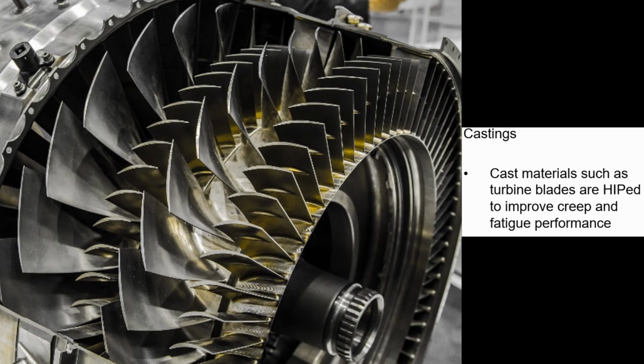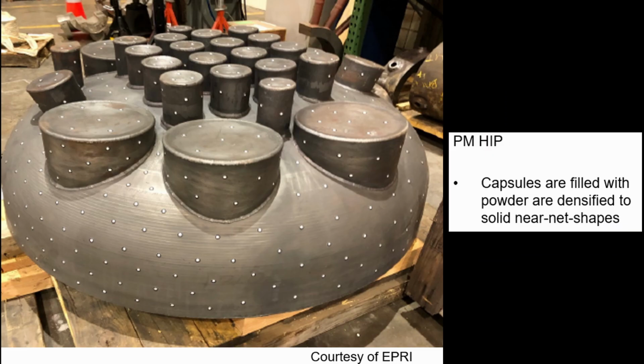One is densification, because castings have been densified since the 60s to improve fatigue life, etc. We have powder capsules, densification of powders, which is, like I say, since the 70s, really, which is really growing right now. It's a very interesting area. And then you have diffusion bonding of materials together, and that can be solid to solid or solid to powder or powder to powder. Basically diffusion bonding different materials together.